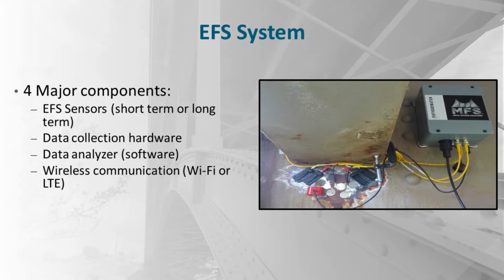The EFS system consists of 4 major components. The first one is the sensor. If you can see in the picture on your right, you see 2 pairs of black plastic on the bottom near the drill stops. Those are the sensors. In this case, they are the short-term sensors that are made to last up to a year. The other one is the data collection hardware. That is the gray box that you see on the top right of the picture. And the data analyzer, that is the software that analyzes all this electrical signal coming from those pair of sensors. That is actually not shown in the picture, but it's that black wire that is connected to the gray box that is somewhere else near where the inspector is. And the wireless communication, so you can monitor or assess the activity of the crack remotely.